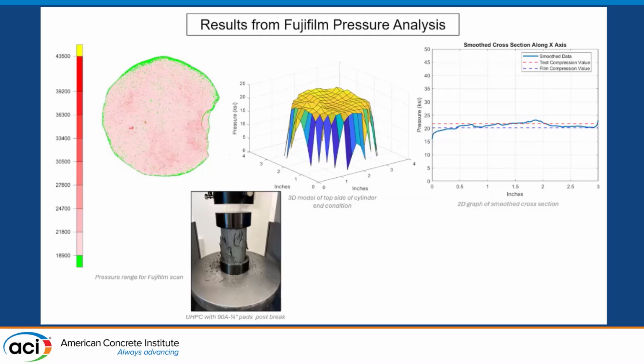And just by looking at the scan, we can estimate that the compressive strength was around 20 to 22 KSI. And here's the cylinder that was associated with this film scan. This was taken from the top of the cylinder, and this was a saw trim cylinder. You can see the 3D model that I was able to develop to show the end condition and how it was interacting with the film and with the pad.